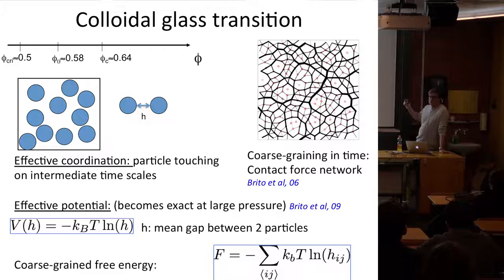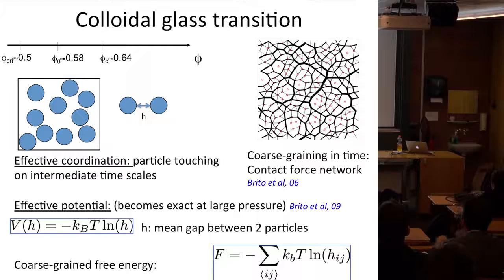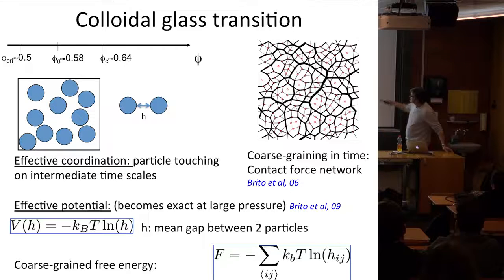Okay, so now I wanted to discuss the question of how do those ideas, that was for zero temperature packing of decompressed packing of particles, what do those ideas tell you for colloidal hard spheres? And in principle, they tell you nothing because for those hard spheres, the energy landscape is completely flat, strictly speaking, right? Or you have infinite walls, but there is nothing much a priori you could say. So what's the idea to apply this kind of reasoning? The idea is to do some kind of time averaging. So think of being in the glass phase here, for example. Particles are rattling around very rapidly, but the system cannot relax. The particles are not moving to large distances, they cannot diffuse away.